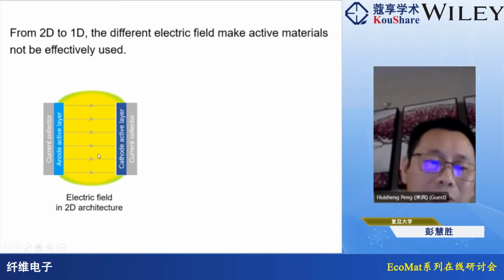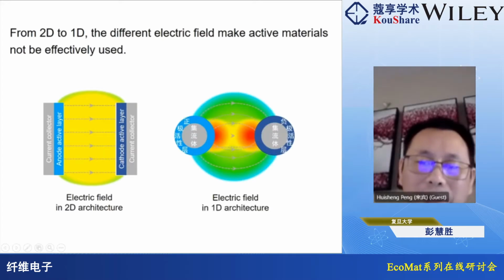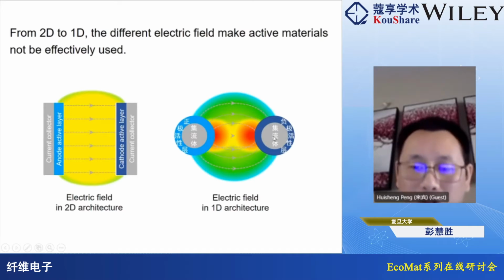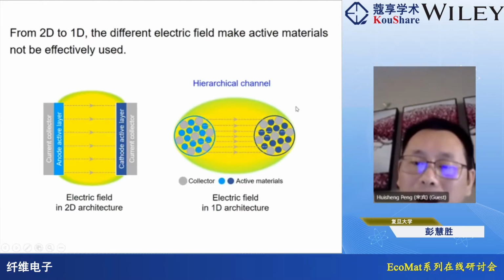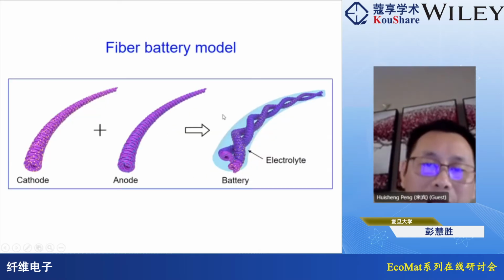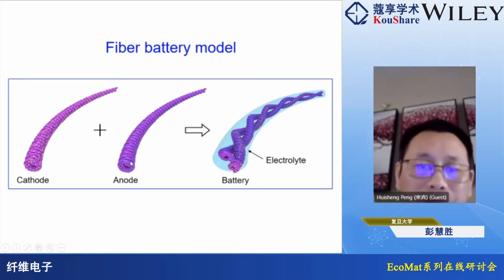And here is the electric field for this planar battery. And here is the case for the electric field based on two fiber electrodes. It's not uniform and it's not easy to match the active materials. So based on the simulations and the experiments, we show that if these fiber electrodes are designed with hierarchical aligned channels, then it's possible for them to form a uniform electric field. So then we try to design this fiber battery model by designing these unique fiber electrodes.